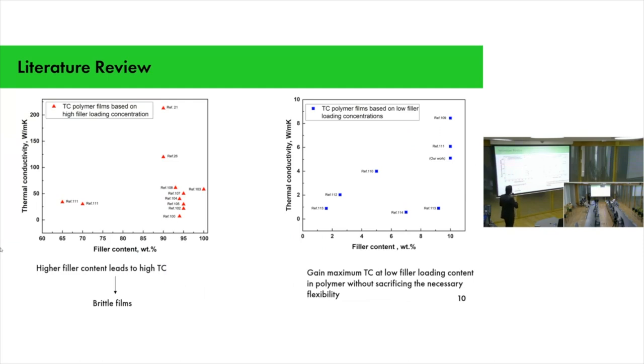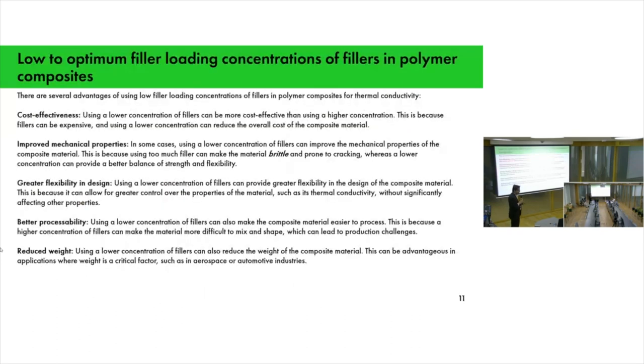If you use a high filler loading concentration, then there is a big probability that the film will turn brittle instead of having ductile behavior. This is due to the fact that the higher filler loading concentration induces agglomeration inside the polymer system. Whereas if you use a low filler loading concentration, you achieve a lower thermal conductivity, not as high compared to the literature, but you can gain the necessary flexibility that you require. So the idea is to use low to optimum filler loading concentration in polymer composites.